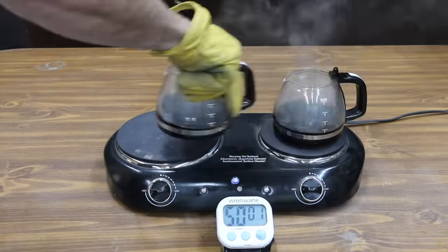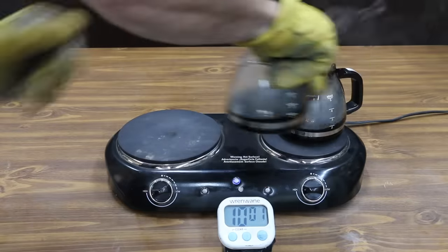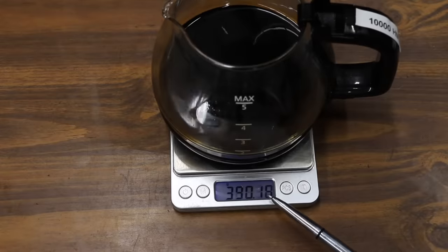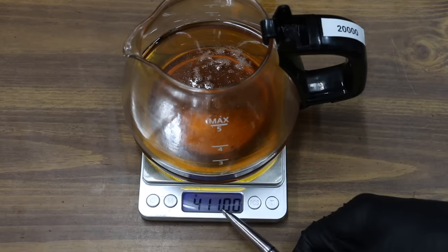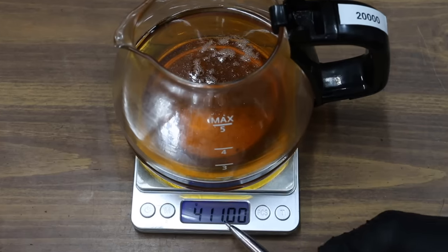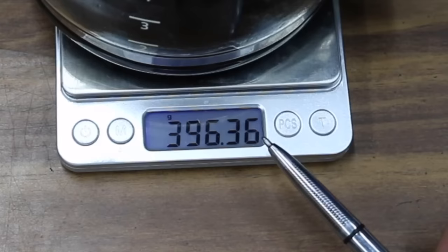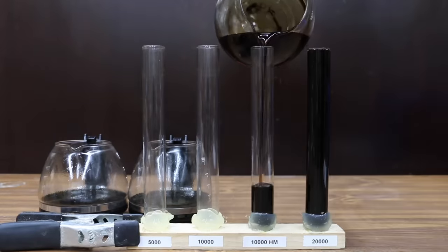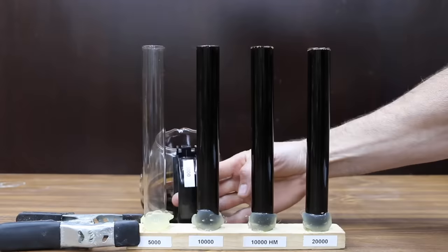Both oils seem to be putting off about the same amount of vapor. The oil was rotated every 10 minutes for two hours. The high mileage oil started at 404.69 grams and now weighs 390.14 — a loss of 14.55 grams. The 20,000-mile oil started at 411 grams and now weighs 396.36 — a loss of 14.64 grams. So both 10,000-mile oils and the 20,000-mile oil all performed very close to the same, suggesting the base oil is either the same or very similar for all three full synthetics.